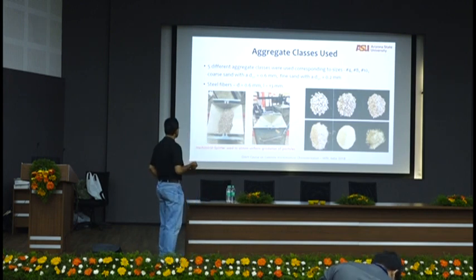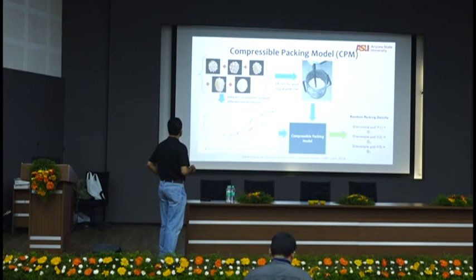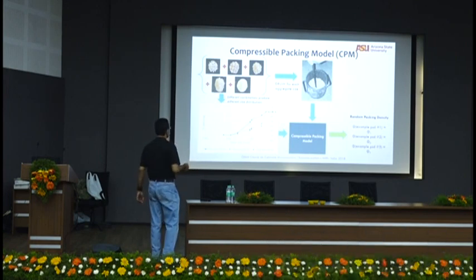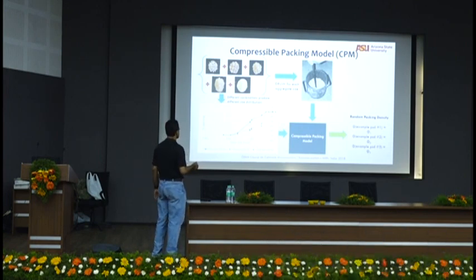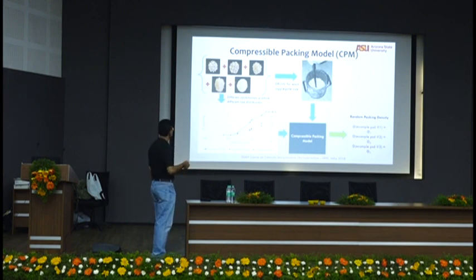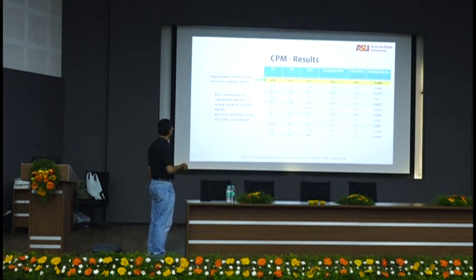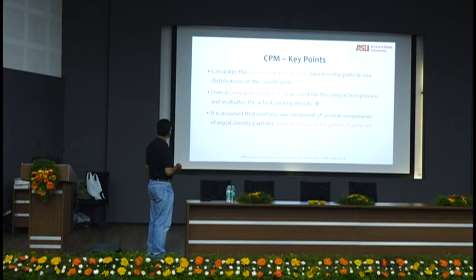Okay, a mechanical splitter was used, so we got all these aggregates. And then we did a compressible packing model. We used dry rodded unit weight, got the combined size distribution of the aggregates, put it in the model, and got different packing densities for different combinations. I'll show you in the next slide. A lot of different combinations. I think we did 885 combinations.